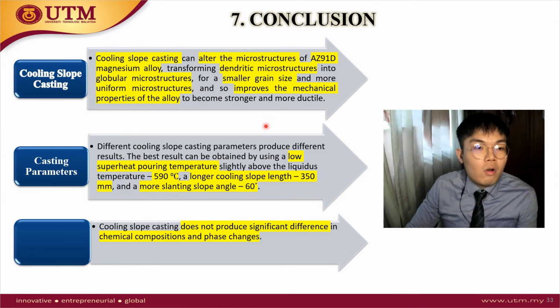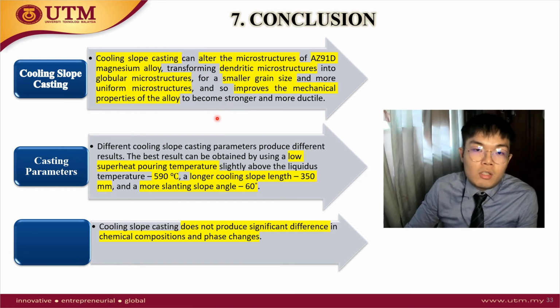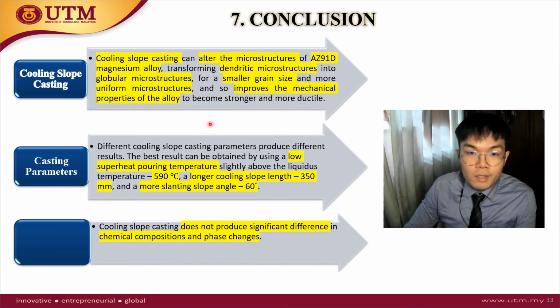So with all of that, we can conclude cooling slope casting can alter the microstructures of the AZ91D magnesium alloy, transforming its dendritic microstructure into globular microstructure, or a smaller grain size and a more uniform microstructure, and so improve the mechanical properties of the alloy to become stronger and more ductile. Secondly, the different cooling slope casting parameters can produce different results. The best results can be obtained in cooling slope casting of AZ91D by using a low superheat pouring temperature slightly above the liquidus temperature, which is 590 degrees Celsius, a longer cooling slope length, 350 millimeters, and a more slanting cooling slope angle, 60 degrees. And thirdly, cooling slope casting does not produce any significant difference in chemical compositions and phase changes.